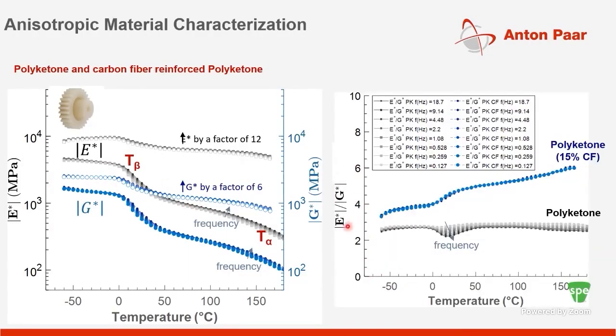If I plot this ratio of E over G as a function of temperature for a pure polymer like polyketone, you can see it's between 2 and 3, with a slight frequency dependence, but nothing out of the ordinary. But for the carbon fiber reinforced polyketone, it varies almost from 3 to 6 times, and it is temperature dependent. So again, we see how you can characterize anisotropic materials with a device like this.